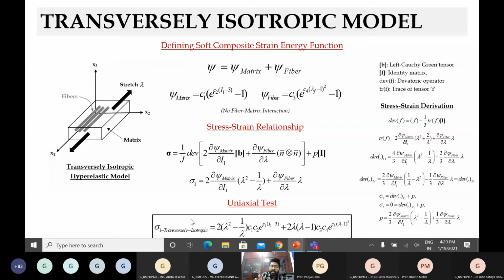So all the hyperelastic models, be it isotropic, transversely isotropic, or anisotropic, which I'm going to show you in a second, they all boil down to two things. They might look like very difficult equations, but they're actually very simple. They're basically curve fit equations. This is an equation between the stress sigma and the stretch lambda, and everything in between is a bunch of constants which needs to be found out through curve fitting.